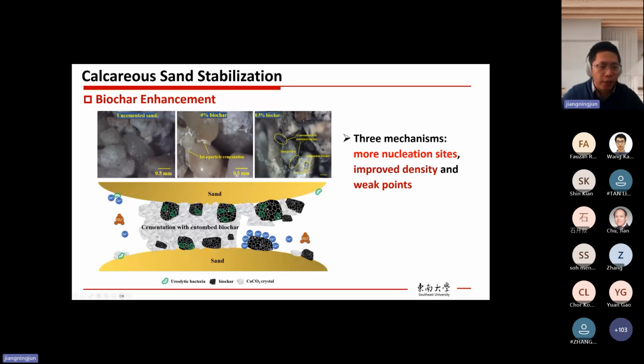Okay, then finally, we also took some microstructure photos to see why biochar could help to improve the soil strength. The first one is uncemented sand. The second one is cemented sand without biochar. And the third one is with 0.5% biochar. For this one, we can see a lot of small dots, right? They are powder-shaped biochar. And we believe these small dots serve as extra nucleation sites for calcite precipitation. That's why we see more cementation formed in the biochar case.